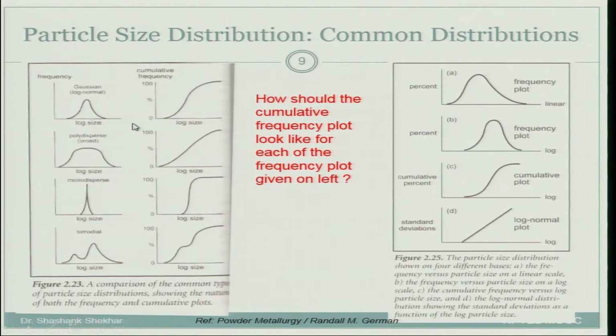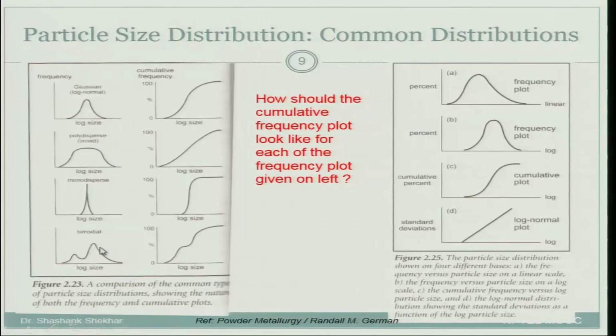However, like I said, log normal is the most common when you have particle size from one particular method. Let us say you mix particles from two different methods, or obtained under two different conditions. In that case, you may as well get a bimodal distribution, and so on.